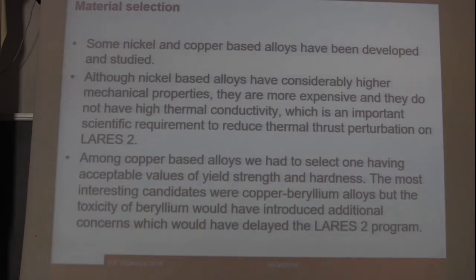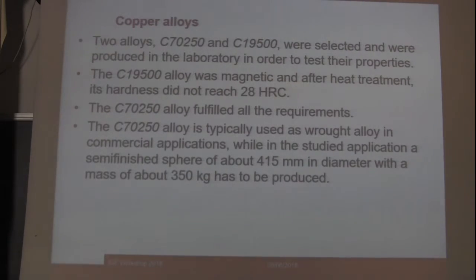Among copper alloys, we had to select one having acceptable values of yield strength and hardness. The first candidate we selected were copper beryllium alloys, but the toxicity of beryllium would have introduced additional concern that would have delayed the LARES-2 program. So among copper alloys, we selected two particular alloys, the C70-250 and the C19-500, that were produced in the lab and were tested to know their properties.